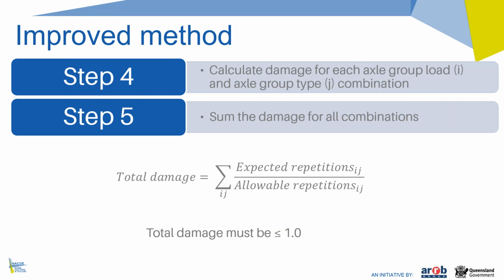The asphalt fatigue damage is then calculated for each combination of axle group type and load. This is done by dividing the expected repetitions, which is the design traffic, for that combination by the allowable repetitions from step 3. And this is very much the same or similar procedure as what's used in the current Austroads guide for concrete pavements. The total damage is then the sum of all damage for each combination of axle group type and load level. And this must not exceed 1 for the pavement to be acceptable in terms of asphalt fatigue damage.